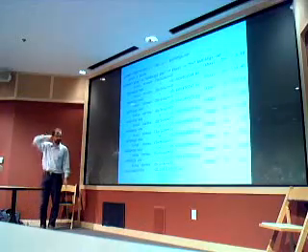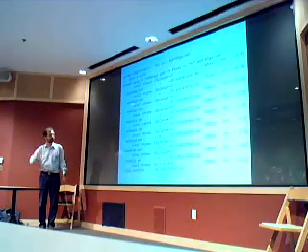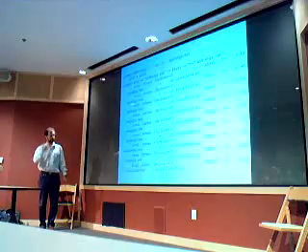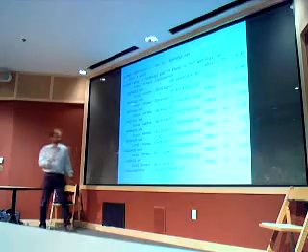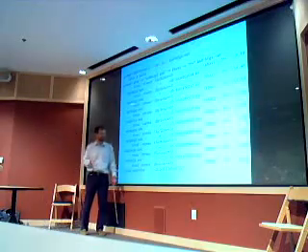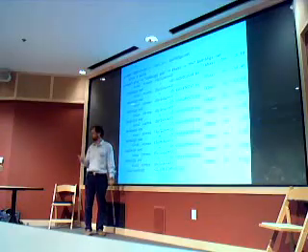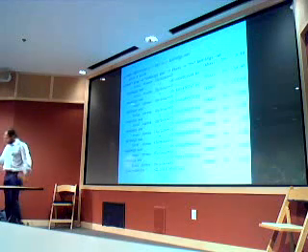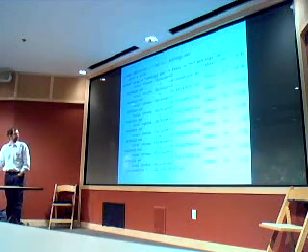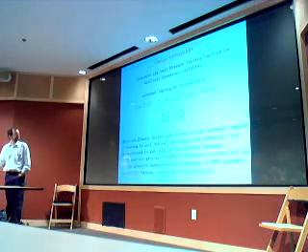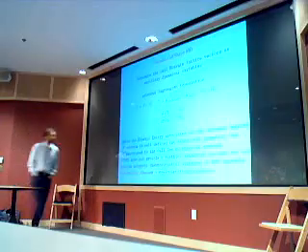And in this particular case, the forces are zero by symmetry, so they do not matter. But in general, when you have lower symmetry systems, the real stopping criteria that matter are the forces and the stress, because the total energy is easier to converge.